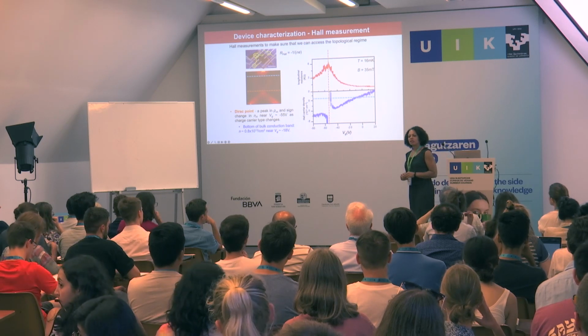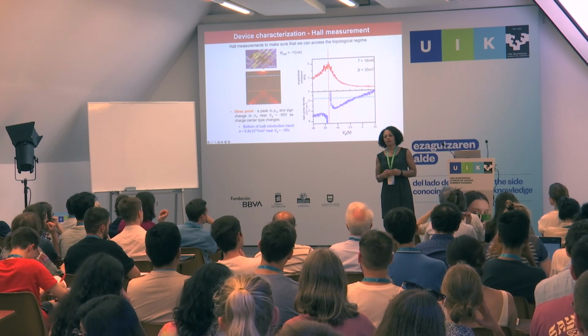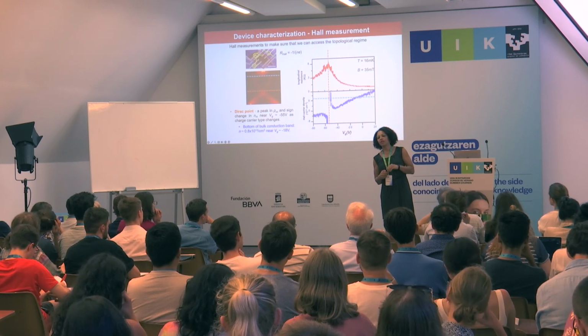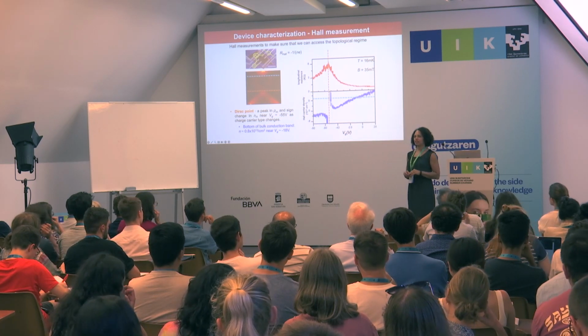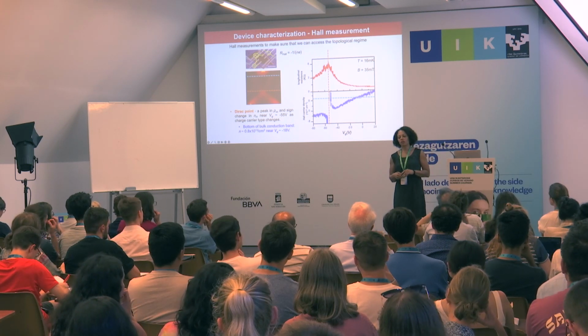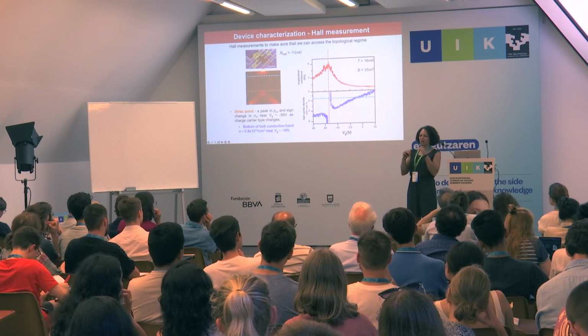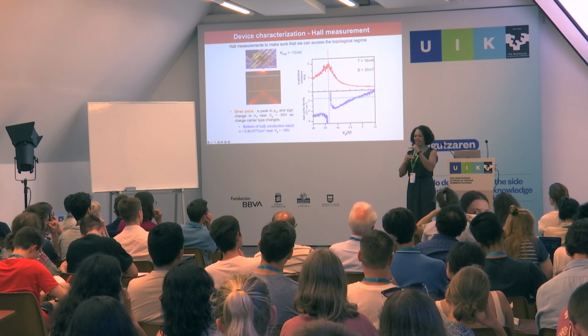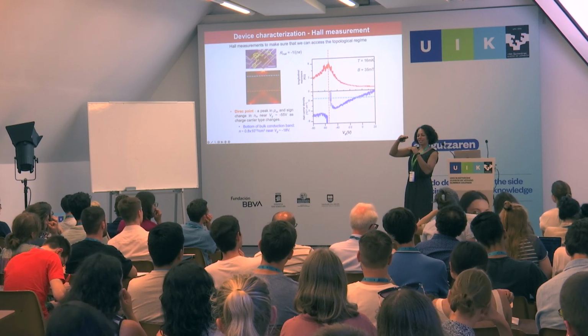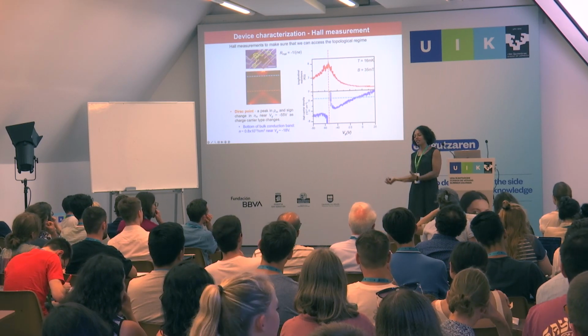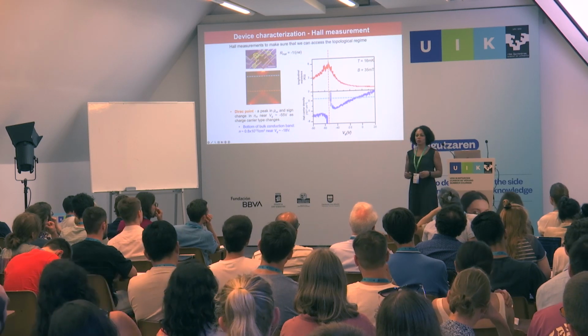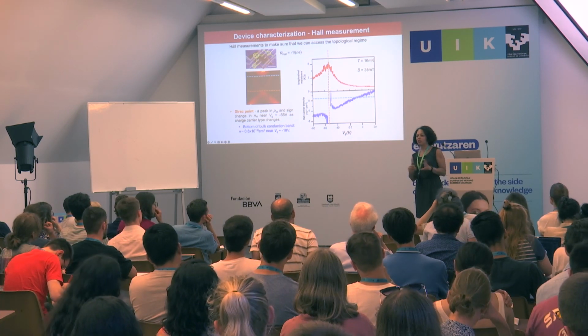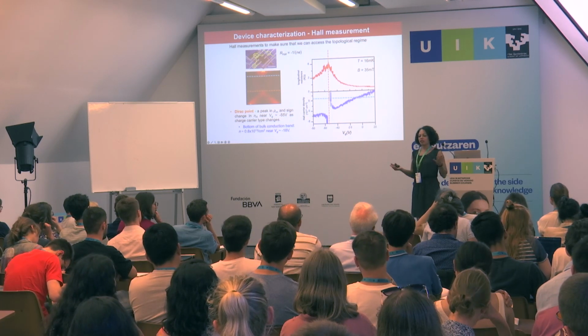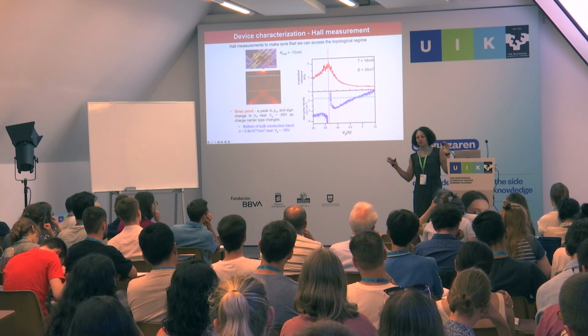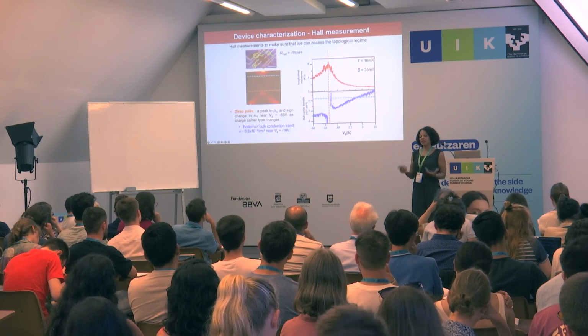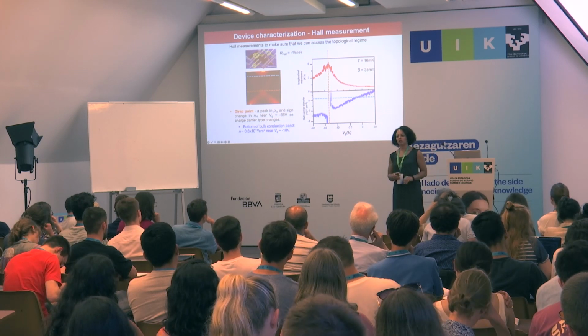Do you see on the thinner plates some kind of hybridization between the top and the bottom layer? If we make them less than about 8 nanometers, yes. So we always try to go above that. Our goal is to go above 12 nanometers, so we don't get hybridization, and below 20 nanometers, so that we can gate them uniformly. It does require some fine tuning because we use exfoliated flakes, and I'll say why later. We find that we just get cleaner surfaces this way, and there are also issues in the MBE-grown ones with hybridization at the interface with the substrate that we want to avoid. We like using exfoliated flakes, but there's a small range you have to work really hard to get in.